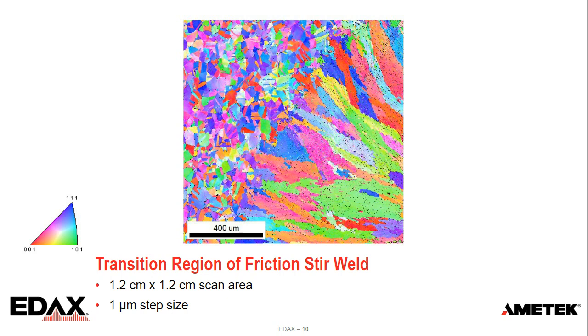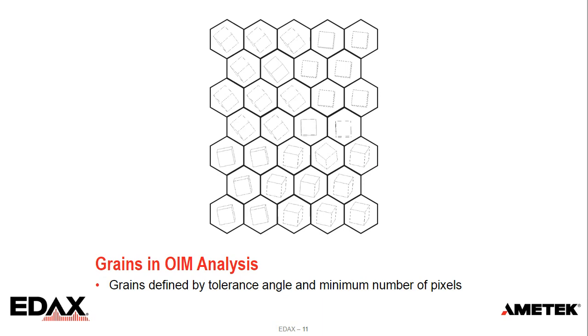Once we have those orientations, what we do with EBSD and with OIM is we typically calculate grains. And when we talk about grains, we define a grain in terms of a tolerance angle and a minimum number of pixels. So if we have our measurement grid, and we typically measure things on a hexagonal grid, this puts more of a packing factor of measurement points on a specific area, and each point has 6 equidistant neighbors. So we can sample more neighbors of the same distance for local kernel measurements. We'll talk about that when we talk about some of those metrics.